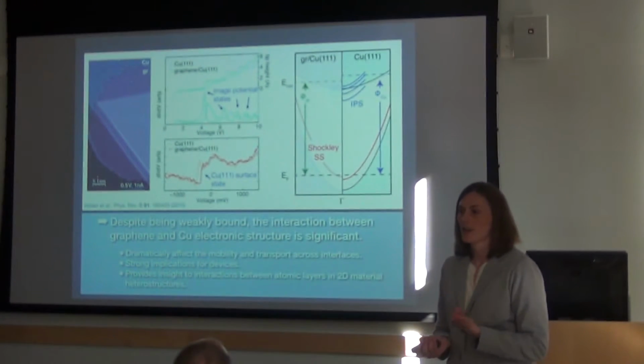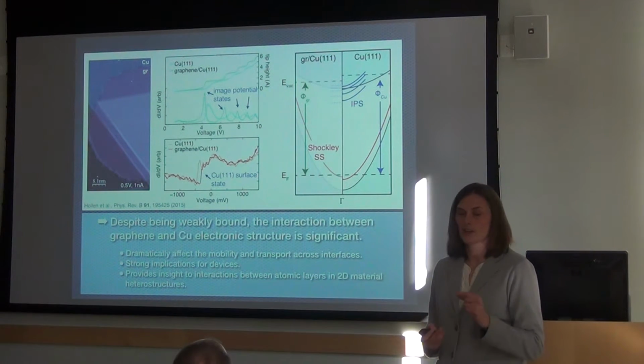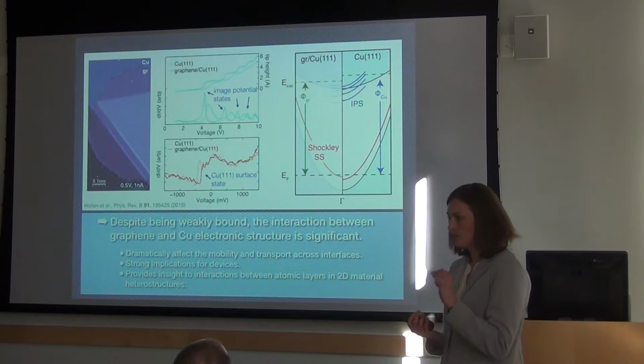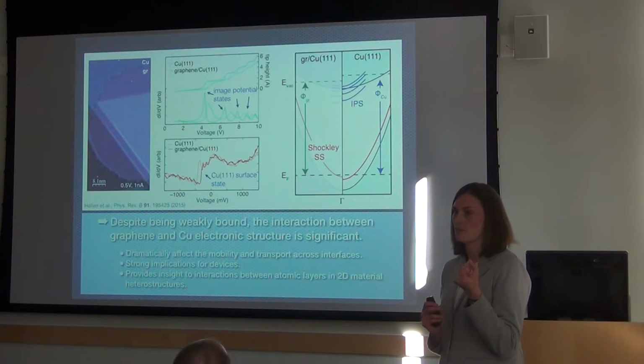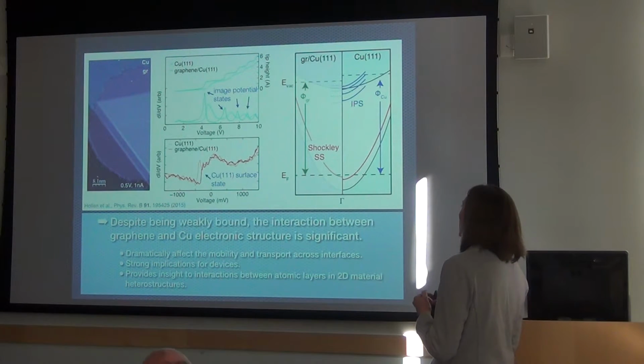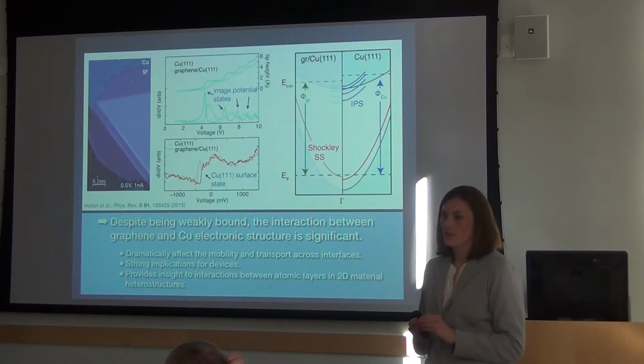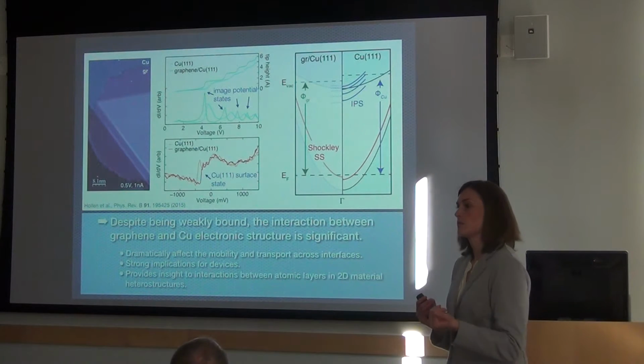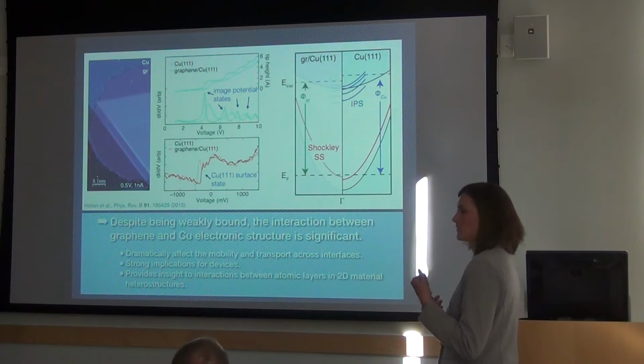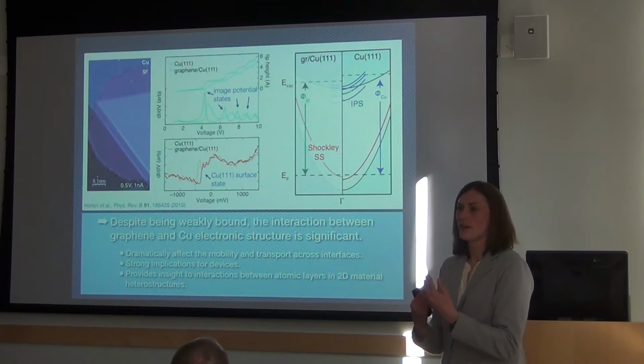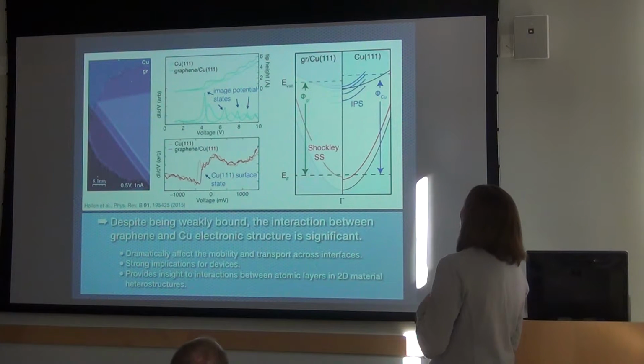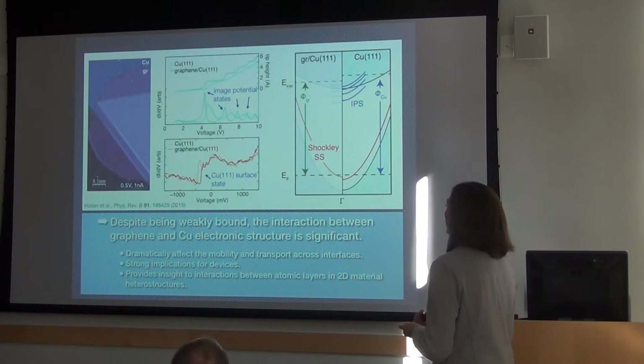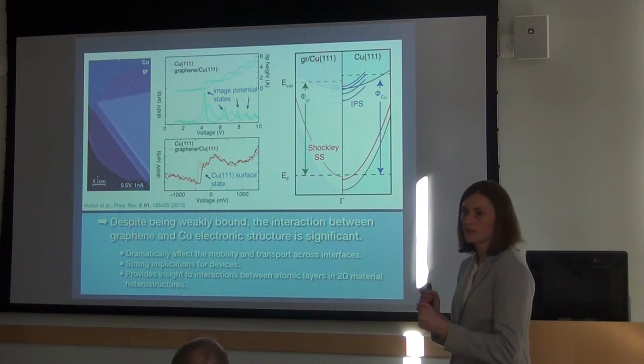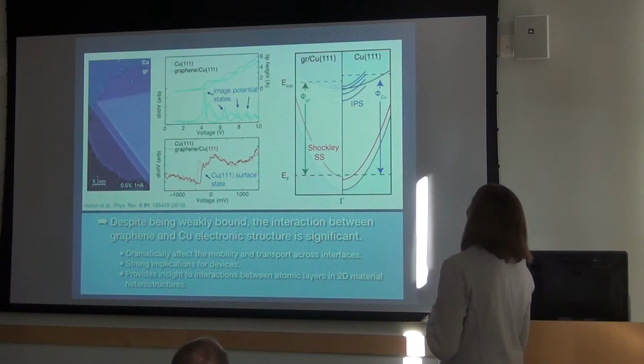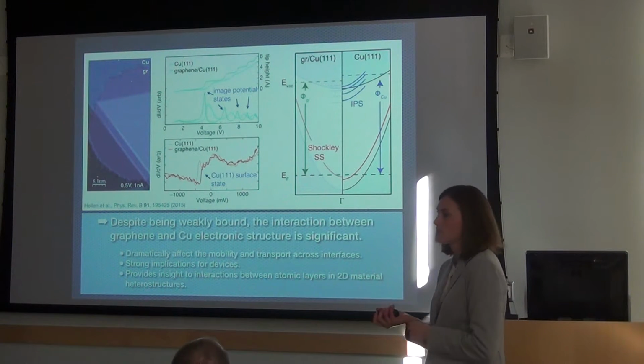But really, the summary of all of these spectroscopic experiments is, okay, what have we learned? We've learned that graphene is modifying the electronic structure of copper. We're not really probing the independent electronic structure of graphene itself, because it's too strongly coupled to the metal. So in these experiments, we didn't see anything that was really independent of the copper. We were looking at how the graphene was affecting the surface states in the copper. And it can tell you a lot about the potential and the interaction between the graphene and the copper. But to us, it told us that it was important that there was copper nearby and graphene was changing the way the states above copper acted. So this is sort of a summary of how graphene modifies the surface states in copper.